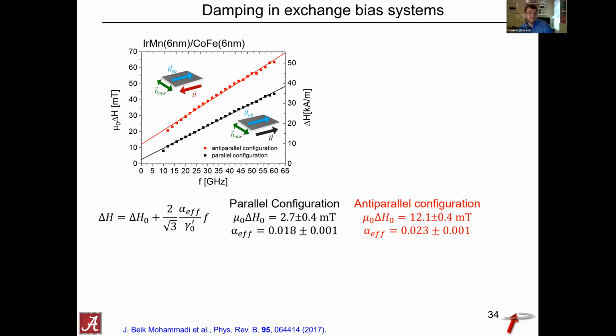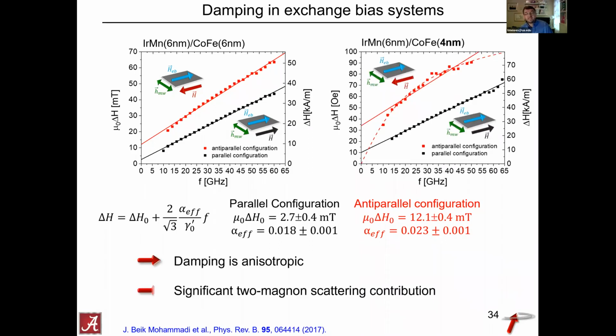But if people pay close attention to the data, they might say, well, maybe a straight line fit is not the right thing to do here, because there's clearly some curvature, at least in the red data. And if you look at a thinner film of cobalt iron, you actually see that this curvature gets much more pronounced here, in particular in the anti-parallel configuration, which is a clear indication of two magnon scattering being present in this system. If I showed you this data with a straight line, you would say, well, that's really not a good fit to the data. Whereas over here, I might just get away with it.